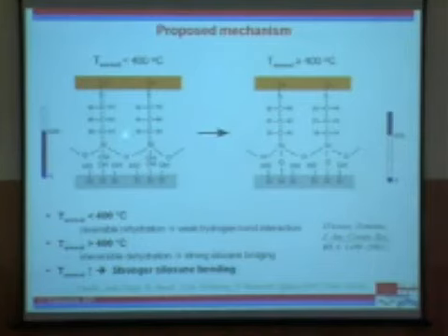At low temperatures, when you anneal it, this part of the bond actually stays stable, and this part, however, is unstable. The OH groups that you have on the silicon tend to form Si-O-Si bonds, but they revert upon cooling.